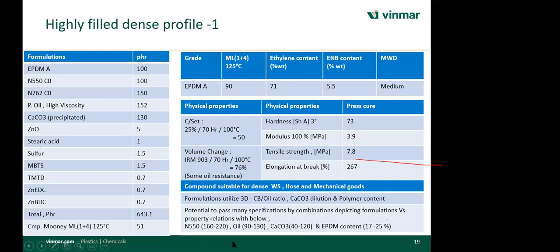If you see the last line here, this is the maximum you can load, and you can get all these properties. You can make a combination. Instead of loading 250 PHR, you can load carbon black from 160 to 220 PHR, and similarly adjust the oil from 90 to 130 PHR, and calcium carbonate, the mineral filler, from 40 to 120 PHR.